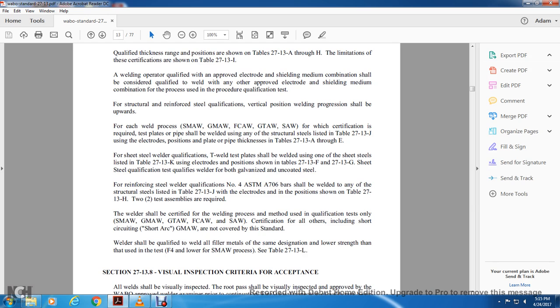For reinforcement steel welder qualification, number 4 ASTM A706 bars shall be welded in any of the structures listed in Table 2713J, with electrodes in the positions shown in Table 2713H. 2 test assemblies are required. The welder should be certified in the welding process of the qualifying test only: shielded metal arc welding, gas metal arc welding, gas tungsten arc welding, flux core arc welding, submerged arc welding. Certification does not include others such as short-circuiting arc gas metal arc welding not covered by the standard.